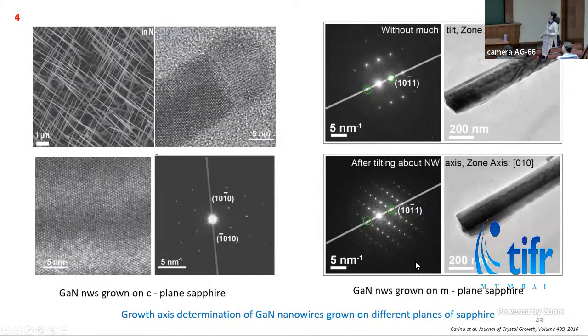So checking the growth direction is a little tedious because we have to make sure that the crystal is oriented properly with respect to the zone axis. Then we have to collect two diffraction patterns in the same zone axis, on some different plane of the same zone axis. And we have to do this on several nanowires to confirm the growth direction of the nanowire.